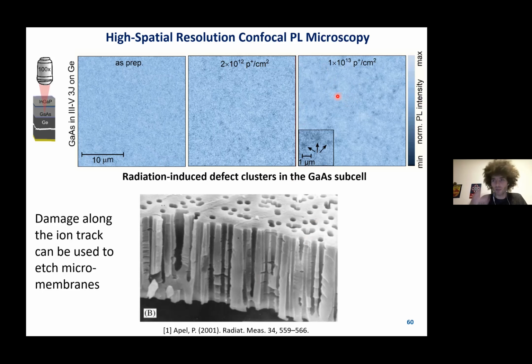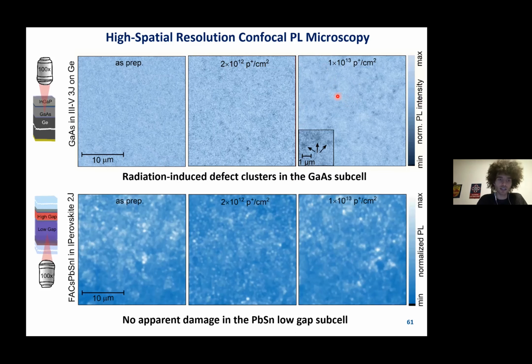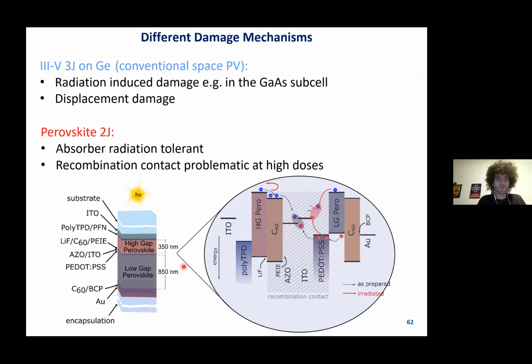All right, so we of course did the same for the perovskite, and now I'm directly jumping to the low gap perovskite because that one was damaged the most. However, we don't see the appearance of any dark spots, but of course, perovskite is not epitaxially grown and is a polycrystalline material. So it's also hard to see. But overall, we think that damage in III-V semiconductors is quite different to damage in perovskites.